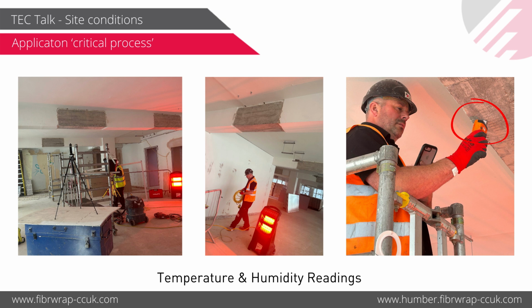So the site conditions, obviously, are perfect in the summer weather, but we have to do various checks before we can apply carbon fibre. The carbon fibre is applied in certain environmental and climatic conditions. You need a minimum of 4 degrees centigrade temperature to apply FRP. Humidity should be less than 85%. As you said, in the winter months, it's very difficult to get that kind of weather naturally. So you have to create an artificial environment and enclosure, where you put the heaters on and raise the temperature if required.